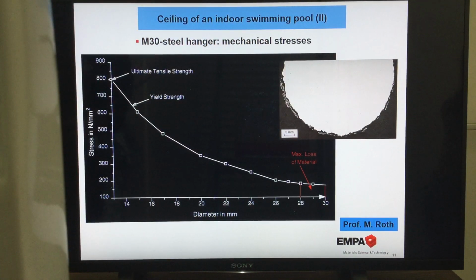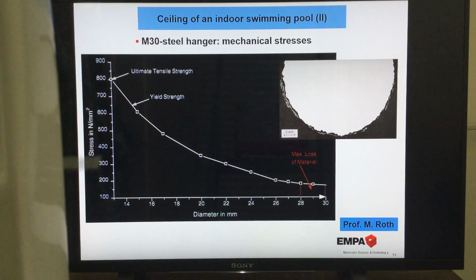And you see something else before we come to the layer, that compared to the Uster case from before, this is our original stress in our steel hanger. It's in the range when we go to here to about, let me say, 160 megapascal. And you see here in this line, the yield strength, I told you that was 640 megapascal and the ultimate tensile strength 800. So we are very, very safe. We were in our design very far away from the critical amounts of the stress.